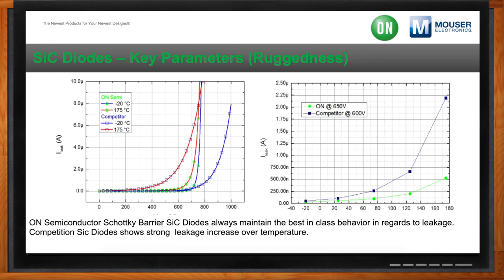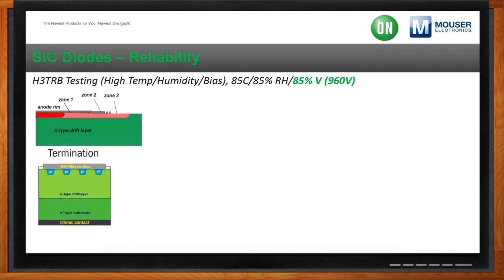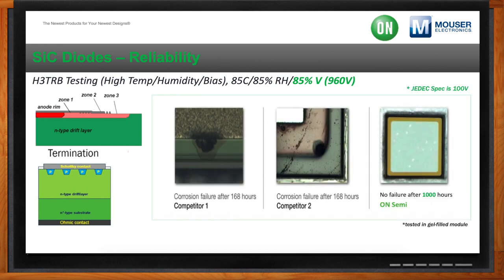Cool. Okay. So then let's talk about that last one, reliability. Well, reliability is arguably the most important. And I think a big thing is that the JEDEC committee is still going through creating the specs for silicon carbide as well as gallium nitride because they're new. And so one thing that we did is we took our H3TRB test, which is high temperature, high humidity, and high bias, and we ran them all at 85%. So we have 85 degrees C, 85% relative humidity, and we did our voltage at 85%.